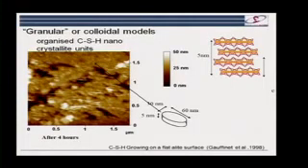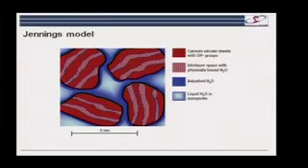So this is another piece of work where people claim that these particles are separate. This is an atomic force micrograph taken after 4 hours, and it's claimed to show calcium silicate hydrate, little bricks here, growing on the surface of C3S. From that, we have this model, which was published about 4 or 5 years ago in Nature Materials, which shows this idea of these blocks.